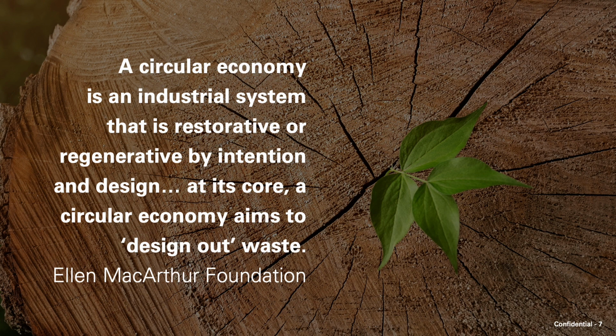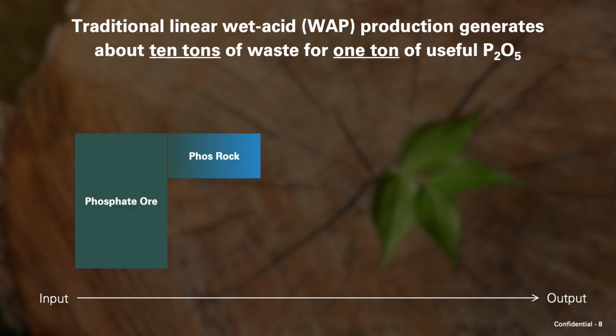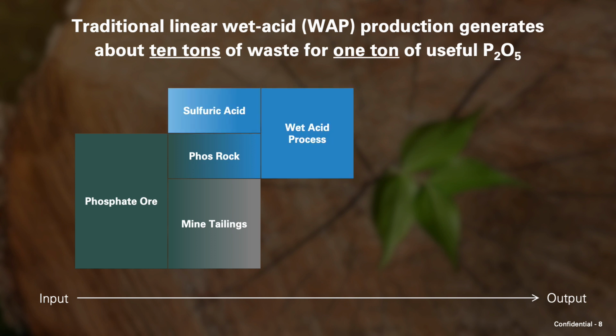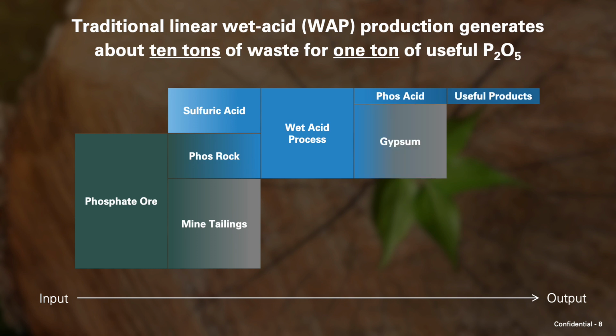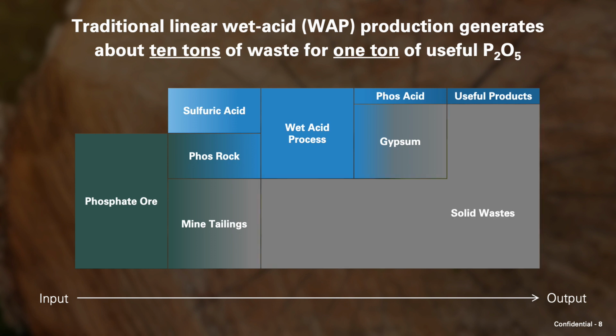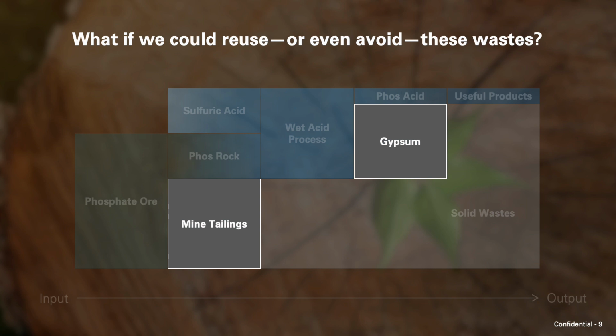Well, there are many definitions of a circular economy. The definition shown here gets at an essential concept. We need to design out waste. So where does waste come from in the phosphate sector? Well, we start with mined phosphate rock, which we then beneficiate to make the useful phosphate rock for the wet acid process. And this generates a lot of mined tailings that contain valuable P2O5. Then we add sulfuric acid, and that feeds the wet acid process, which does indeed make phosphoric acid, but it also makes a lot of phosphogypsum. So for each ton of useful phosphate products, we get about 10 tons of solid wastes. What if we could reuse or even avoid these wastes?